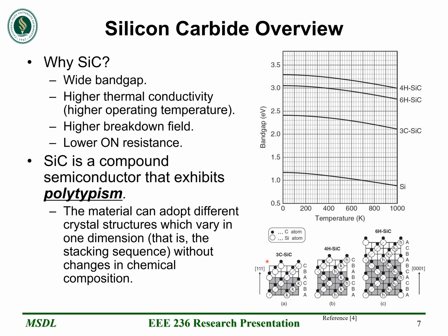So for example, 3C silicon carbide means that it has 3 different layers that repeat periodically, and this creates a cubic structure. That's what the C stands for: cubic. In contrast, we have 4H silicon carbide, which means that there are 4 layers in the stacking sequence which repeat, and this creates a hexagonal structure. And lastly, we have 6H silicon carbide, which means that there are 6 layers in the stacking sequence, and this one also makes a hexagonal structure.